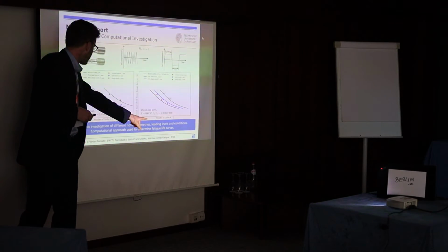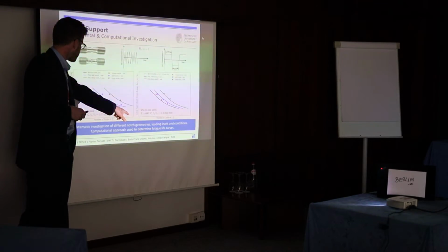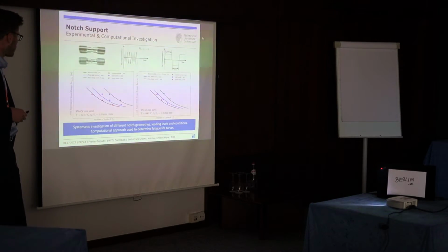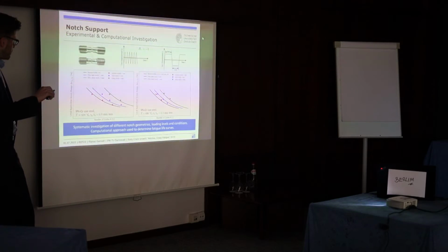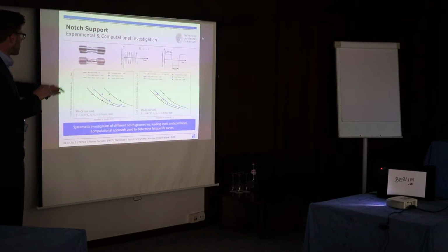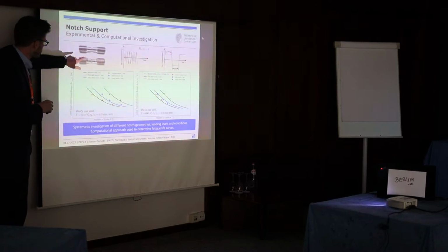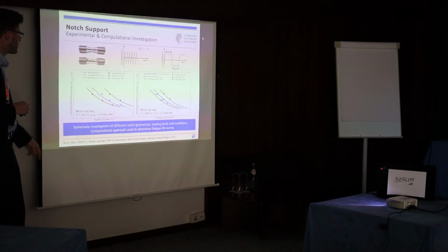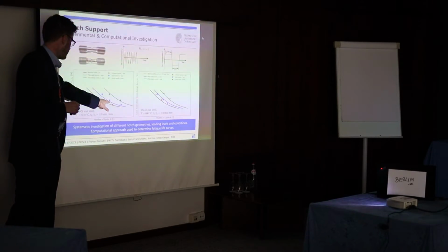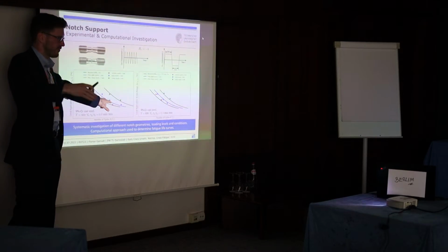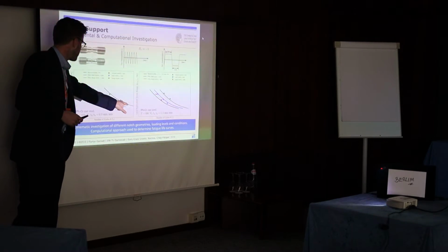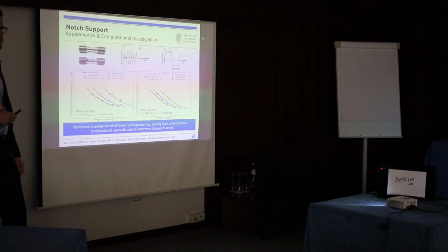The standard fatigue life curve is this black one here, and the red markers belong to the standard tests, the blue markers belong to the mild notch, and the green ones to the sharper notch. And you see already that the cycle number for crack initiation, or for a crack depth of 1 millimeter, is much higher in the notched specimens.